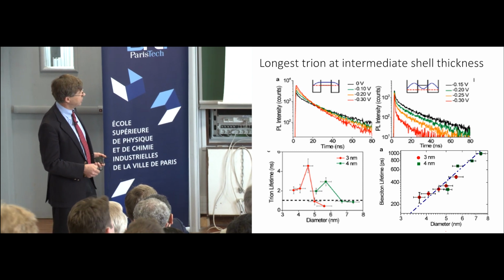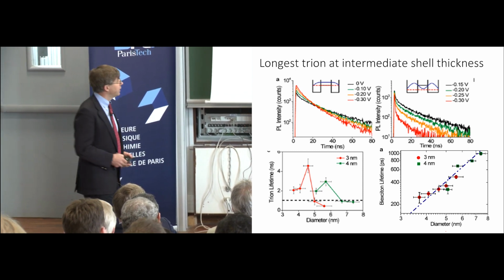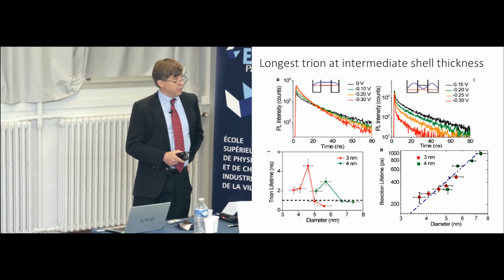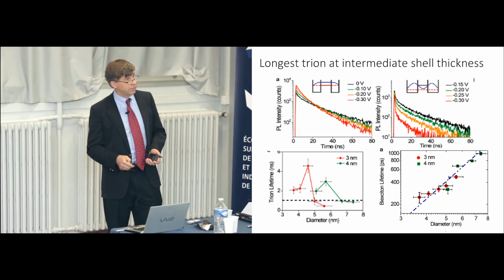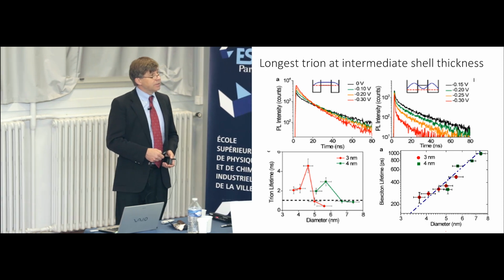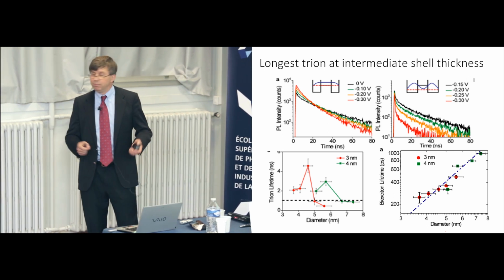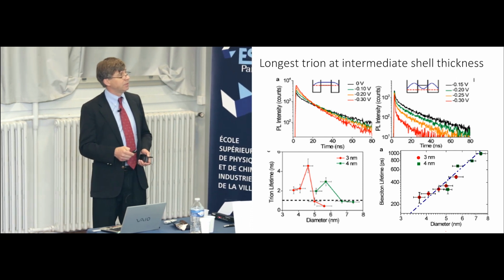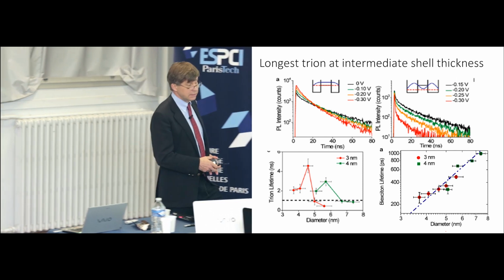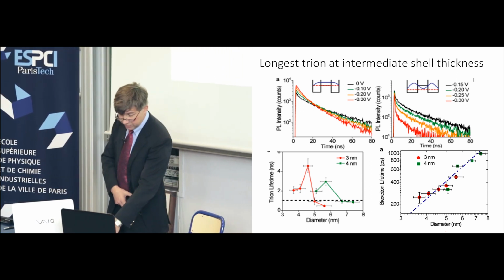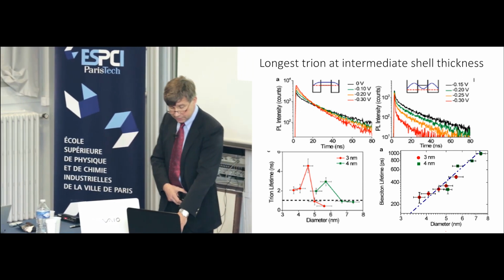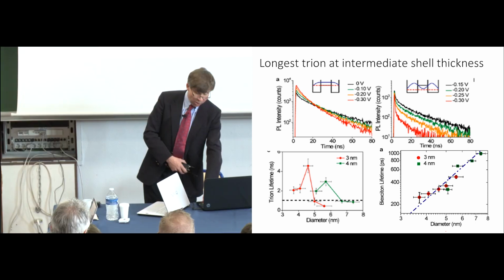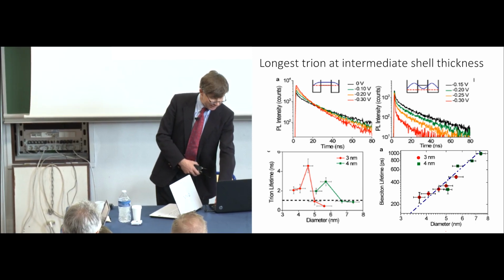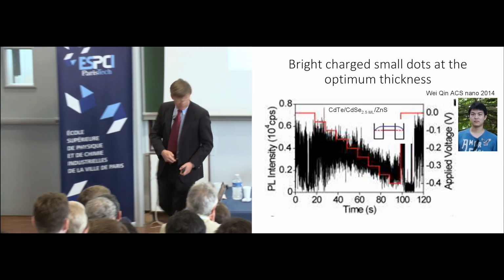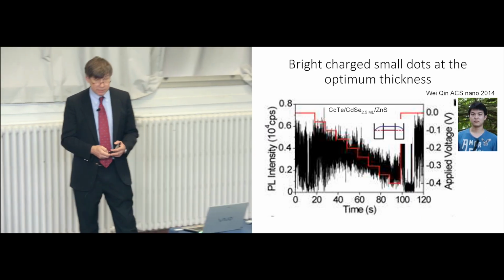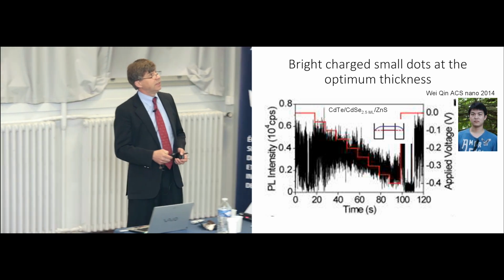Biexciton lifetime shows this simple monotonous behavior, matching more or less the observations by many previous experiments, in particular the work of Viktor Klimov on the scaling with size. So there was this kind of bizarre thing where the negative trion lifetime is non-monotonous, but the biexciton lifetime is not. And I think it's still a topic of discussion. The paper was rejected initially by ACS Nano. Eventually, I pleaded with Andrei Rogach, so it's nice to know people in the field, and he managed to publish it. This is verification of the beneficial effect of that intermediate shell thickness on the single dot level.